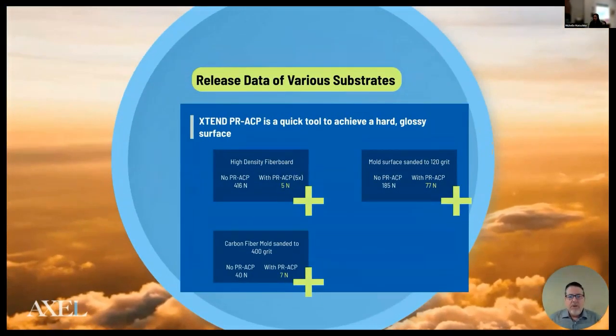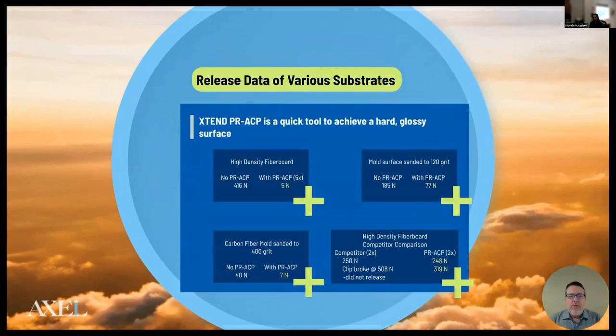The fourth panel we show in this webinar is where we did our primer on one side of high density fiberboard and our competitor on the other side, just 2 coats, and then sealer and release were applied the same, 1 coat of each to both sides. And they were both about the same on the first, but as reapplication occurred, the primered and release side continued to release, and the competitor's side did not.